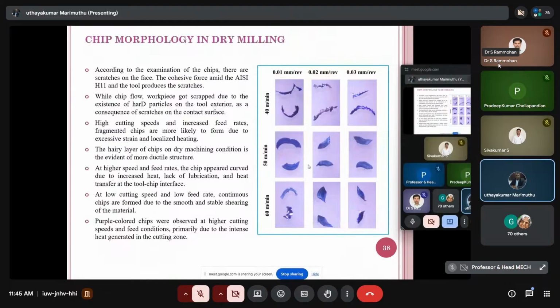And it goes on. Now you can see the chip morphology in the dry machining process under each condition. It is very important, the metallurgical evidence for the chip morphology at each machining condition. According to the examination of the chip, there are scratches on the face. The cohesive force aimed at the workpiece and the tool produces the scratches. While the chip flows, the workpiece gets scraped due to the existence of hard particles on the tool exterior.